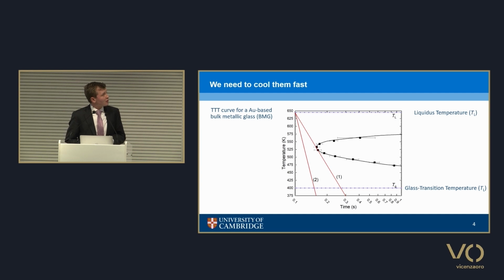So when we form a metallic glass, we take it from the liquid state and we want to cool it very quickly to avoid crystallization. And so we can measure these properties using what's called an isothermal time-temperature transformation curve, which I've measured here for one of the gold-based glasses.